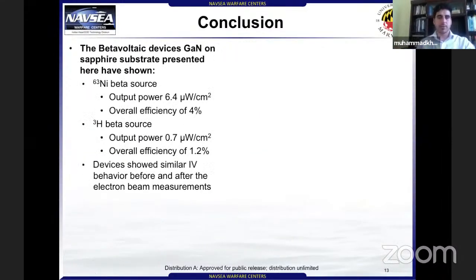In conclusion, we made betavoltaic devices, with gallium nitride film grown on top of sapphire substrate, and we got an output power for nickel 63 of 6.4 microwatts per centimeter square with an overall efficiency of 4%. For tritium, we got an output power of 0.7 microwatts per centimeter square with an overall efficiency of 1.2%.